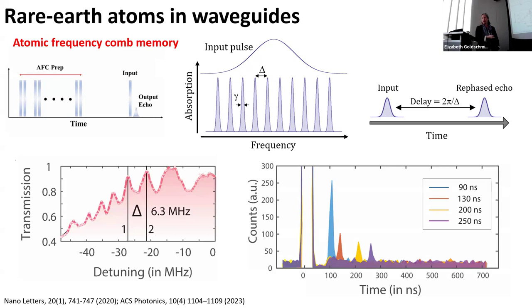Watch this come out. It turns out we couldn't really go past that, even though our coherence time is longer than that, because making a comb with smaller spacings practically in our experiment became very, very hard. And so, in fact, we have a super exponential decay of our very bad storage efficiency, which is due to the fact that our comb got worse and worse as we tried to store for longer and longer times, which is another practical challenge in atomic frequency comb memories. But there are other systems that should be better. This was kind of, thulium isn't great. We had waveguides here, not cavities or anything, which isn't great. So there were a lot of reasons for this first attempt.